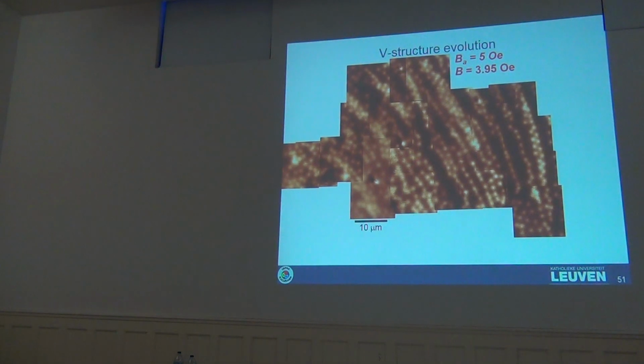Victor, sorry, yes. This is, did you heat and cool down again? Yeah, always. Apply field, and in the field, cool down. And then below TC, you scan. Because if you want to change the field, then again, you warm up, apply a higher field, cool down, and scan again. But this is a kind of a frozen pattern because it's a very, very small field, right? It's a very small field, yeah, but the crystal is actually quite thin, so you have to enhance the effective field by taking into account demagnetizing fields.